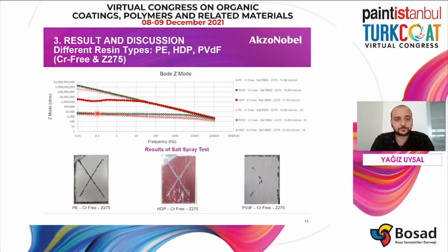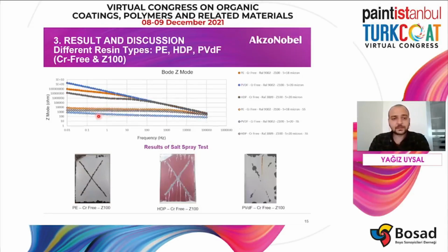We can actually make the same comparison of different resins with the zinc amount of 100 gram, and we have done this similar to the zinc amount of 275 gram. PVDF coating has the highest impedance value, which we can simulate in the accelerated test methods. I mean, it has less blister and rust formation.